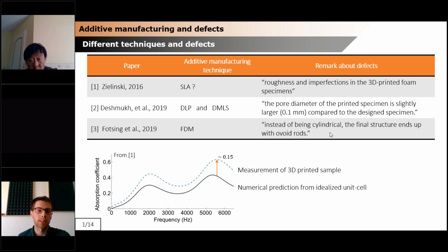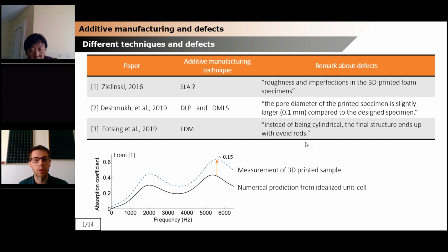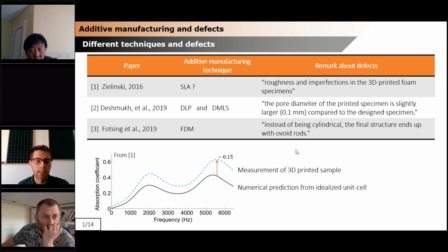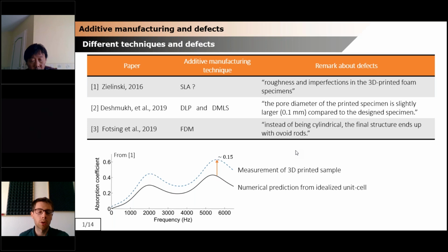So we see in the literature that the porous materials are not exactly as they are supposed to be once they are 3D printed. And what is the impact of the defects on the behavior of the porous material? Well, it tends to increase the intrinsic losses of the material. And in terms of absorption coefficient, for instance, we see that there is an underestimation of the measured absorption coefficient in comparison to what was predicted. So, for instance, here there is a 0.15 absorption coefficient decay.